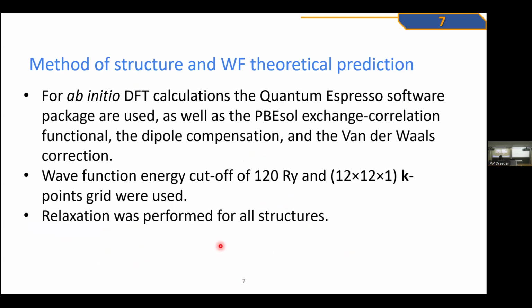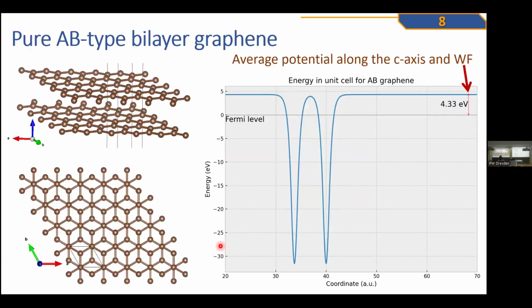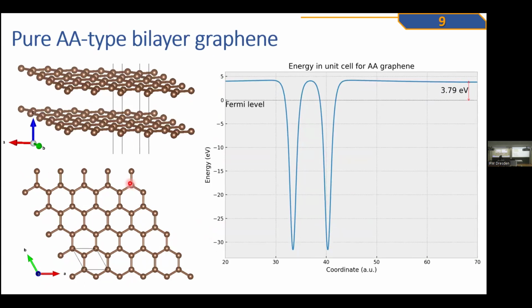For our DFT calculations, we use the Quantum Espresso software package with the PBEsol exchange-correlation functional, the dipole compensation, and the van der Waals correction. Relaxation was performed for all structures. In nature, there are two types of bilayer graphene, AB, like this, and AA, like this. They have a relatively big work function. The graph shows the difference between the Fermi level and vacuum level for such systems, and it is the work function.